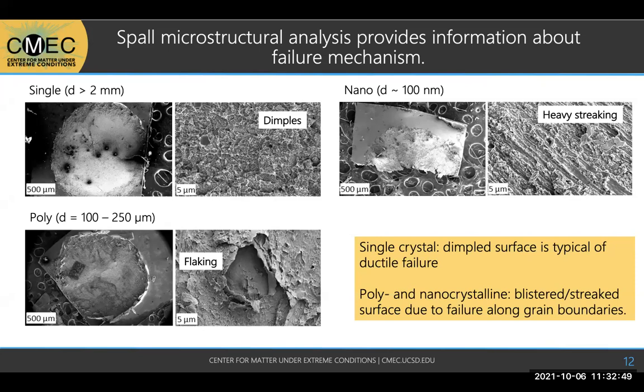So the spall microstructural analysis after the experiments was able to provide information about the failure mechanism. These are the SEM images that I took from recovered samples, and you can see starting in the single crystal samples, that failure surface is really, really dimpled. And that's generally due to the formation of all of these tiny voids that tear the material apart. In the smaller grain samples, the poly and the nanocrystalline versions, we see different failure behavior. It's kind of flaking or streaked. And that gives us more information that these samples failed along grain boundaries. So these were our initial hypothesis. Next slide.